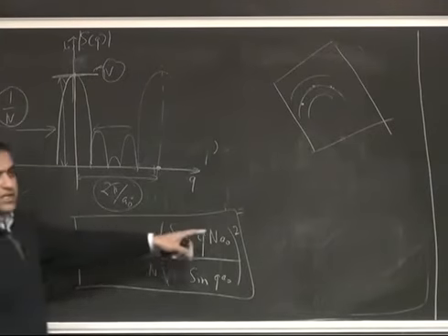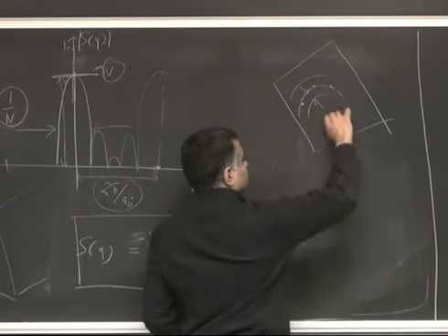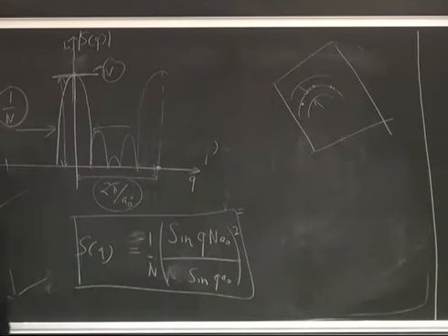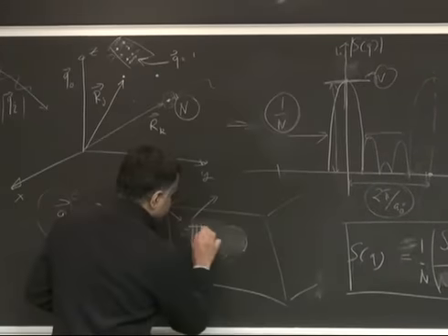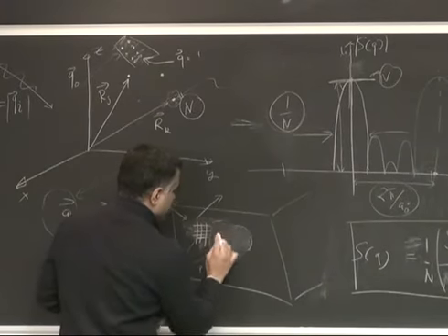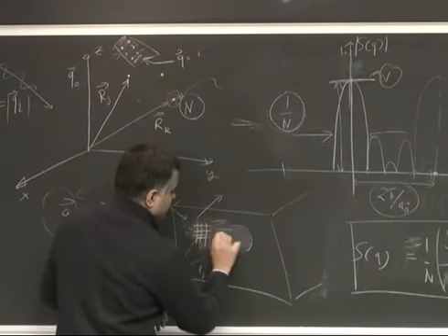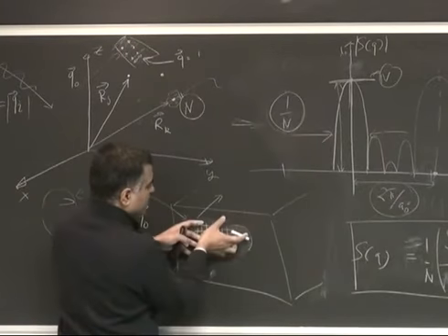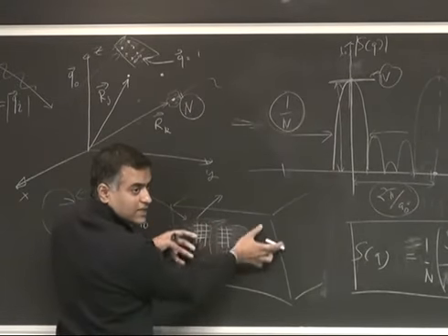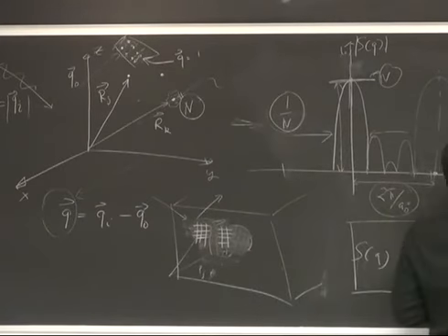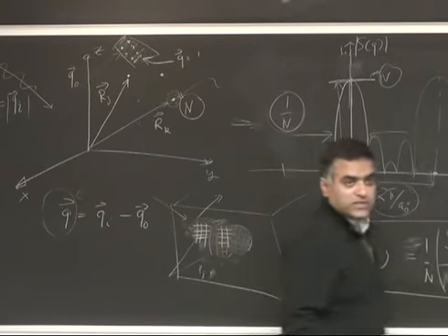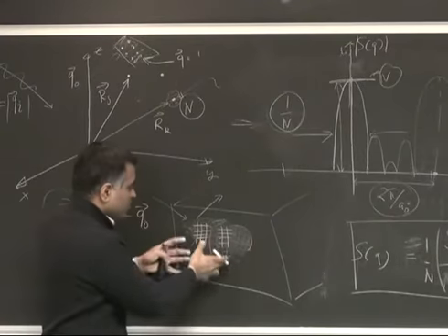The lattice constant is very easily measured because it is the separation between the rings, so you can pick that out as well. And as we discussed, if you had a highly disordered solid, meaning it's mostly crystalline and mostly aligned, but there are breaks in it and grain boundaries, and some parts which are dislocated, one crystal here slightly offset from here, then what you get is still the spots, but they are not very sharp. They are broadened. So you get broadening whenever you have some mosaicity and defects.